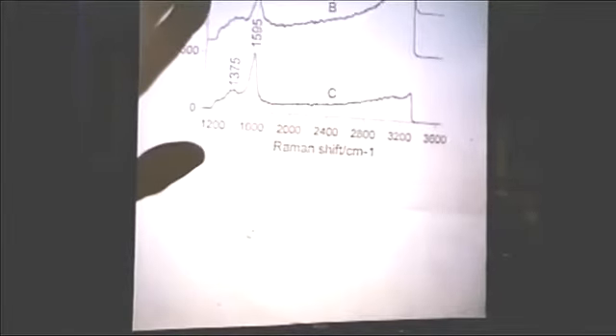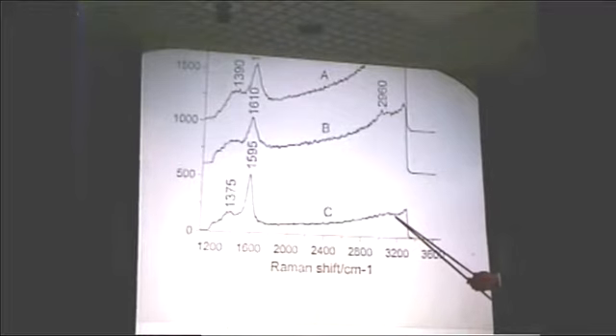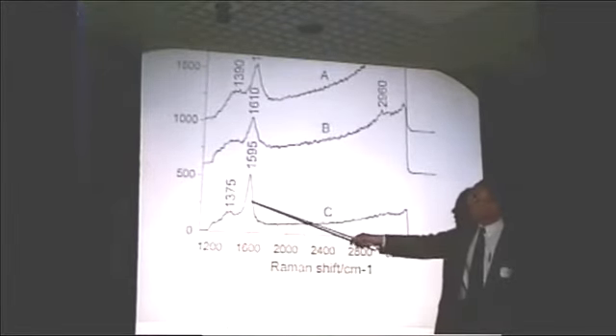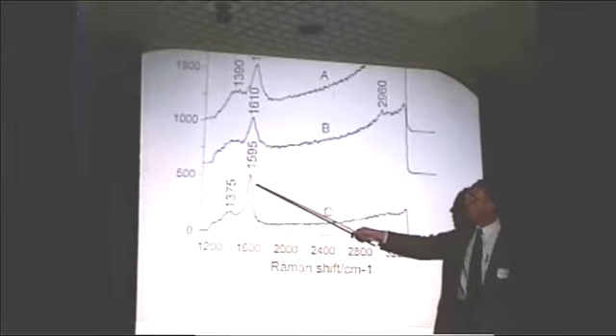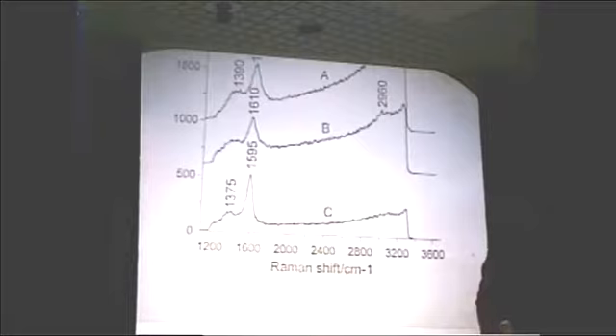And if we then go to 500 degrees C, so that we mimic the treatment that we gave the ZSM5, there's essentially no hydrogen left at all in this spectrum. And the CC stretch peak has shifted down below 1600 wave numbers. In fact, if you look at this spectrum and compare it to spectra for microcrystalline or poorly ordered graphite, they look very similar. So already at 500 degrees C for an hour, the USY has made microcrystalline graphite, whereas the ZSM5 did not. So of course we were very pleased, because that's exactly what we hoped we would see. If you go longer, that coke band peak shifts even lower.